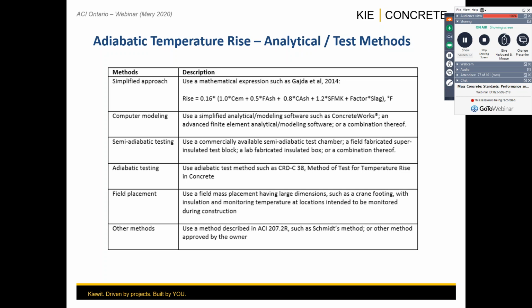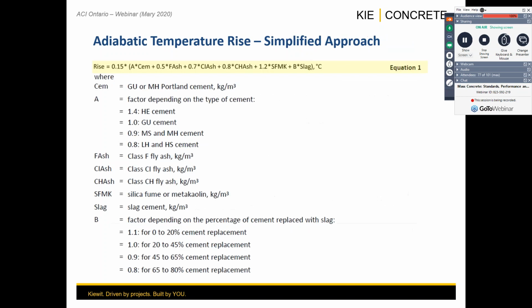It's not going to be a slam dunk. It's not going to be a single unit of measurement that you're going to be able to determine and never go and revise and verify. I always say develop adiabatic temperature rise, and then go and verify what the temperature rise in the field is compared to what you estimated in your thermal control plan, and then start working on your revisions and updates. So you better go and qualify and refine those temperature conditions in the field more appropriately with the performance of the concrete in service. So those are things that you need to understand as you implement that.